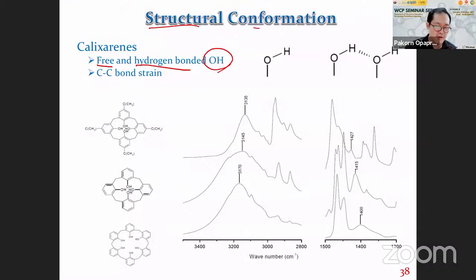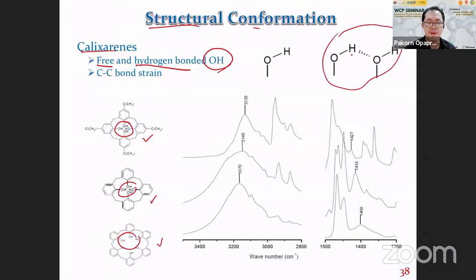and then try to determine the structural conformation from the sample. So if you look at this sample, this cyclic compound called calix-arene has OH group. This OH group can form hydrogen bonding with each other. So if OH group is free, does not form hydrogen bonding, the bond here is quite strong. So we will see peak at high frequency, normally around 3,500. But if OH group forms hydrogen bond with other groups, this bond becomes weaker. Therefore, we see a shift in the peak to lower frequency.